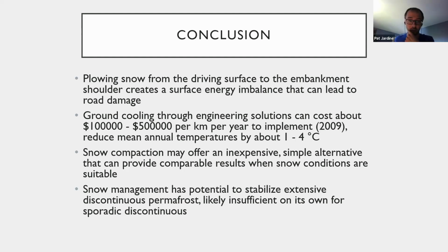And both actually had similar results based on my experiments, since I found engineering solutions typically only cool the ground by about 1 to 4 degrees Celsius. So snow compaction may offer an inexpensive, simple alternative that can provide comparable results when snow conditions are suitable. And it has the potential to stabilize extensive discontinuous permafrost on its own, but moving south into more sporadic permafrost, it would likely be insufficient.